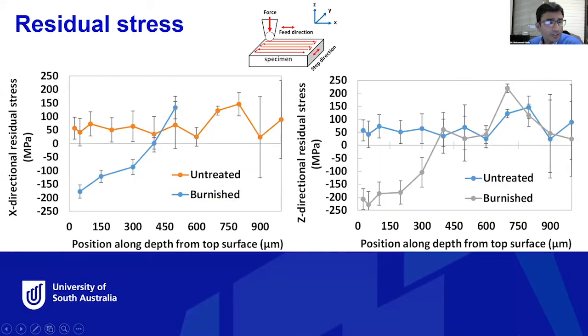We also looked into other mechanical properties, such as residual stress. We can see that by applying the burnishing, we can also induce a compressive residual stress into the top surface, and it decreases as you go down along the cross-section.